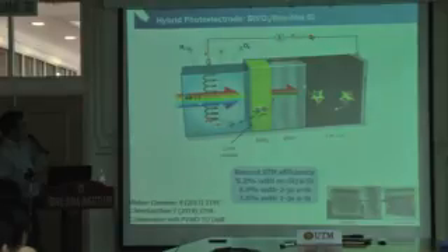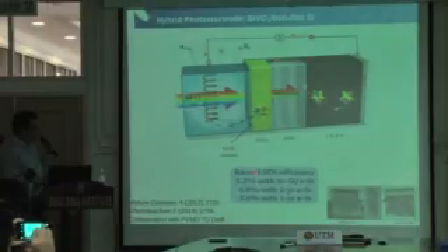Right, so from our work, we have also made a hybrid photoelectrode. We use a metal oxide, in this case bismuth vanadate, BiVO4, and a thin film silicon solar cell, in exactly the configuration that I showed before. The blue part of the solar spectrum is absorbed by the bismuth vanadate, and the red part is transmitted and used by the solar cell. And we got, at that time, this was a year or two ago, a record solar to hydrogen efficiency. We got about 5.2%, 4.9%, and 3.6% with different types of thin film silicon solar cell.